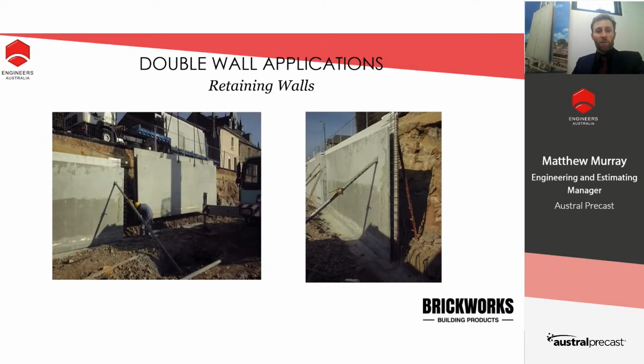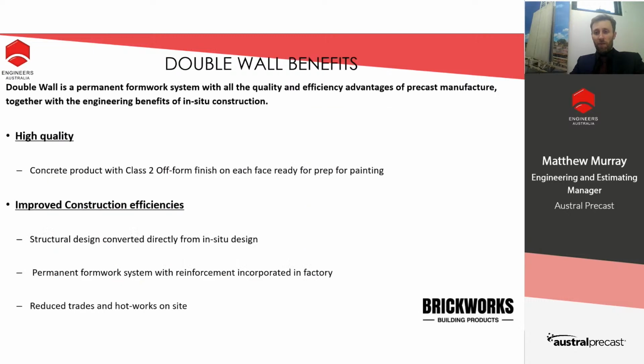Here we have also some retaining walls. We can do cantilevered retaining walls with double wall, which requires essentially a similar footing to what you would have as an in situ construction. Then the main point would be a check by the engineer of the bending moment, and particularly shear, particularly at the joint from the bottom of the panel to the footing. The other thing you can see here is a significantly reduced requirement of earthworks at the rear of the panel in comparison to in situ methods.